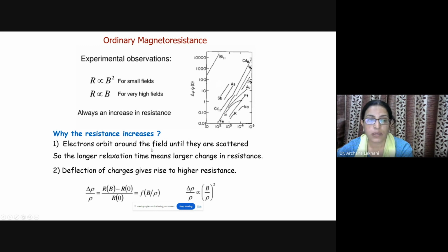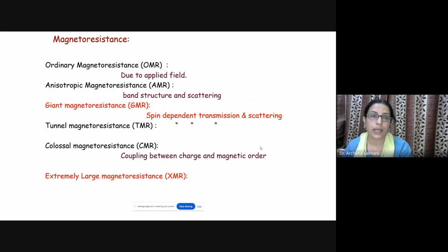And why does it change? Because electrons orbit around the field until they are scattered. In the presence of a magnetic field, we have a longer relaxation time, as well as the deflection of charges gives rise to higher resistance. There are various types of magnetoresistance: ordinary magnetoresistance, anisotropic magnetoresistance, giant magnetoresistance, tunnel magnetoresistance, colossal magnetoresistance. And nowadays people talk about extremely large magnetoresistance, which are very useful materials in technology. In case of ordinary magnetoresistance, in ordinary metals, we get only a very small change in magnetoresistance. When we talk about anisotropic magnetoresistance, it depends on band structure and scattering. It is direction dependent.